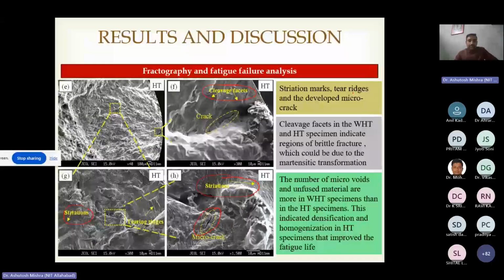All these are available. Cleavage facets in the WHT and HT specimens indicate regions of brittle fracture, which could be due to the martensitic transformation. Then the number of microvoids and unfused materials is higher in the WHT specimen than in the HT specimen. This indicates densification and homogenization in the heat treated specimen, which actually improved the fatigue life.